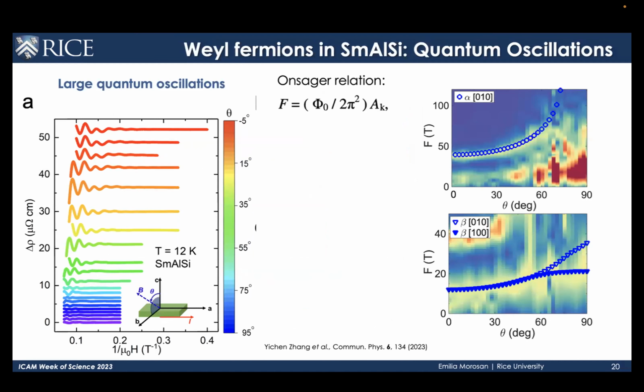So we then complemented the ARPES and the calculations with quantum oscillation measurements. And so sure enough, we observe large quantum oscillations. Here are the Shubnikov-de Haas oscillations as a function of field for different angles of the applied field relative to the crystal direction. And so when we map that with the calculation, we see good agreement for these, what I'm calling alpha and beta pockets, which are some of the predicted Weyl points that I showed earlier.